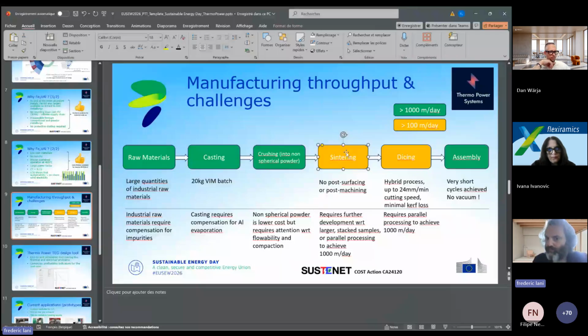So in terms of sintering, of course, the most widespread technology is spark plasma sintering. So we use this. It can have other names depending on the company. We develop the process so that we don't have to post-treat the surfaces, so post-machine them or post-surface them. It means we can dice them right away after the sintering.